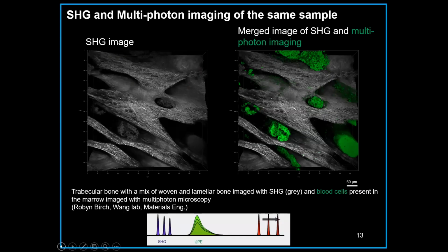So Robyn Birch from the Wang lab has bone, which has a lot of collagen fibers. So with SHG imaging, she was able to see the bone structure. And using the same pulsed laser illumination light, she was able to do multi-photon imaging. Here the green shows blood cells. Blood cells had autofluorescence. And the beauty of this technique is that we use the same pulsed excitation laser at around 810 nanometer wavelengths. Then we set up 2 tunable detectors, one to detect second harmonic generation and another detector for multi-photon.